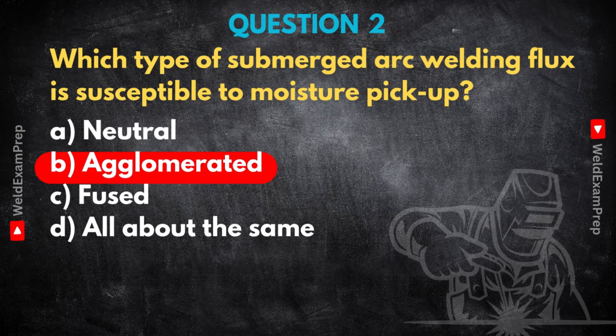Right. Okay. So let's say that agglomerated flux does get damp. What actually happens in the weld? What are the real dangers? And maybe more practically, what makes keeping it dry so tough on a busy site? Oh, the consequences are serious. If moisture gets into the weld pool from the flux, the heat breaks it down into hydrogen. And that hydrogen dissolves into the molten metal. When it cools, the hydrogen gets trapped. That can cause hydrogen-induced cracking, sometimes called delayed cracking, because it can show up hours, even days later. Plus, it massively increases the risk of porosity, little gas bubbles in the weld. Definitely not good.